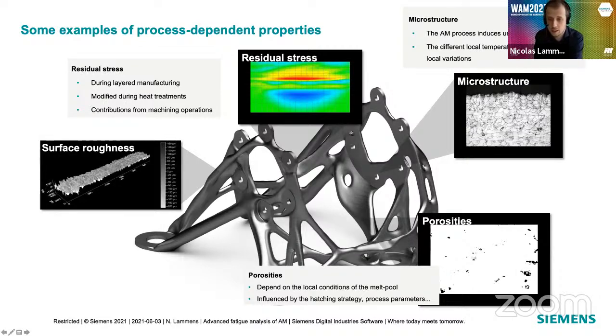And then the final one I wanted to mention is porosities. And here I want to emphasize the local effect of all these properties and how important they can be, because porosities, essentially, are dependent on the local conditions of the melt pool. And those local conditions are affected by the hatching strategy and the processing parameters. So if, for example, you have an overhang where the material tends to heat up a bit more, you could see that you get more porosities in that region than you get somewhere else in your component. And then depending on the type of loads you apply to your geometry, those porosities could either be in a very critical region or could be meaningless.